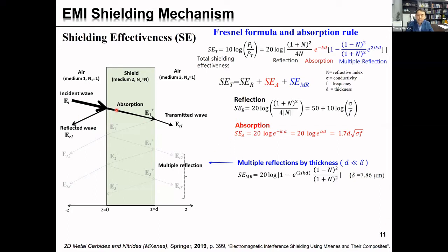Generally, reflection and absorption are functions of material properties, including conductivity, permeability, and permittivity. For conducting shielding material, the reflection and absorption are strongly governed by conductivity. Larger conductivity produces stronger reflection and stronger absorption, and finally, larger shielding effectiveness.